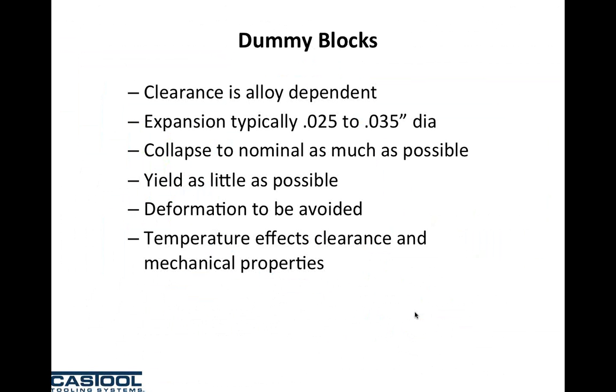Deformation is typically because of time and pressure, so we want to be able to cope and deal with pressure and time through design. Temperature affects clearance. If you put a cold dummy block in your press and you start extruding, you've increased the operating clearance substantially. You're probably going to get immediate blow-by. You also change the mechanical properties of the dummy block.